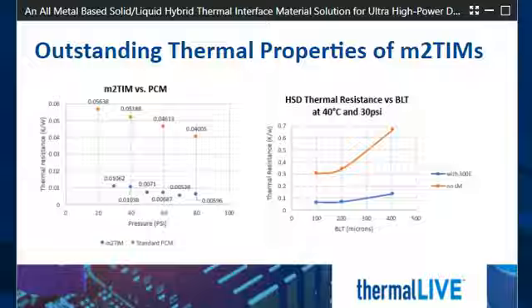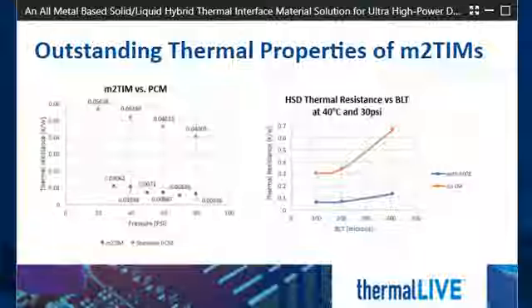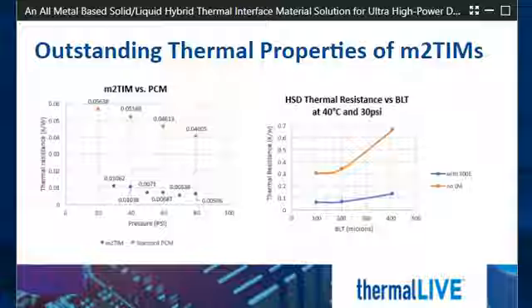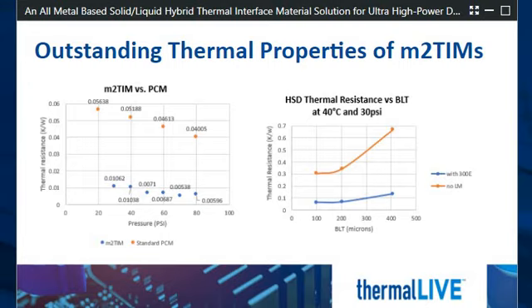Solid-liquid hybrids won't pump out. A power cycling process of 0 to 80 watts with a peak junction temperature of 105 Celsius was applied on M2 TIM. After more than 20,000 cycles, none of the material was pumped out and we couldn't see any huge degradation in performance.